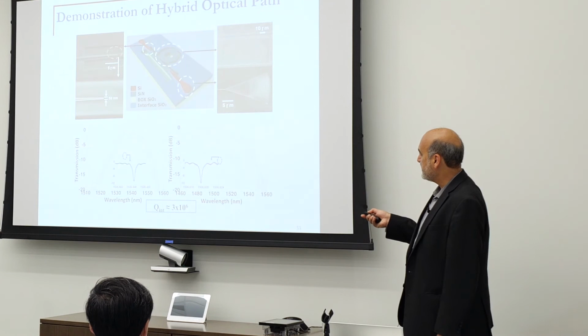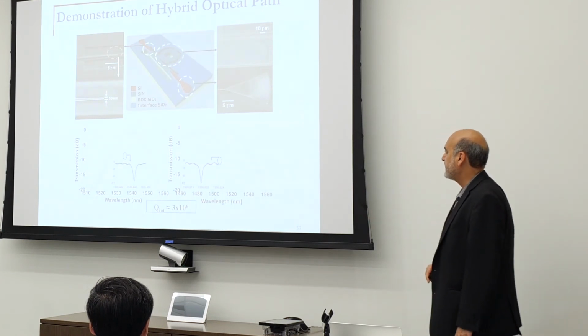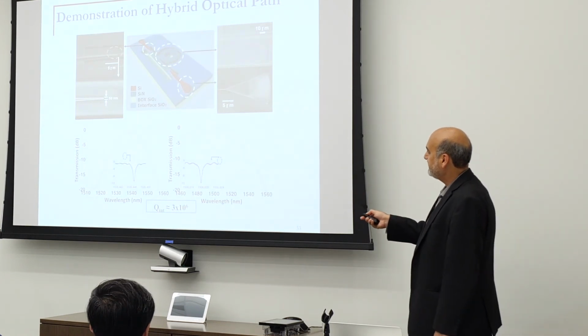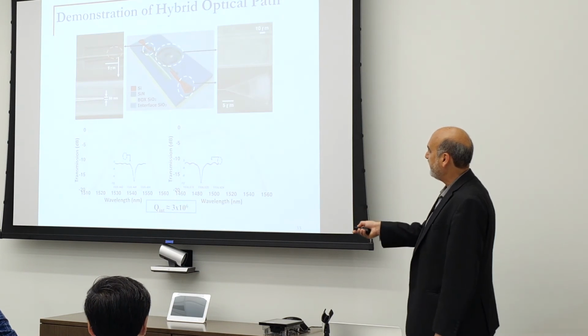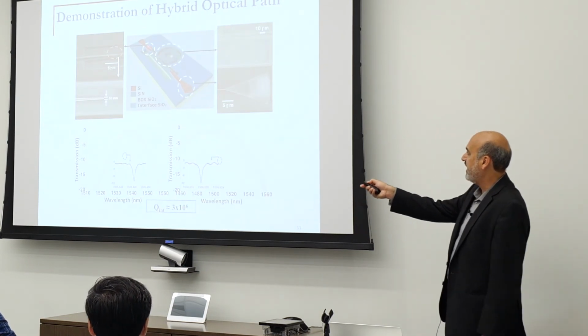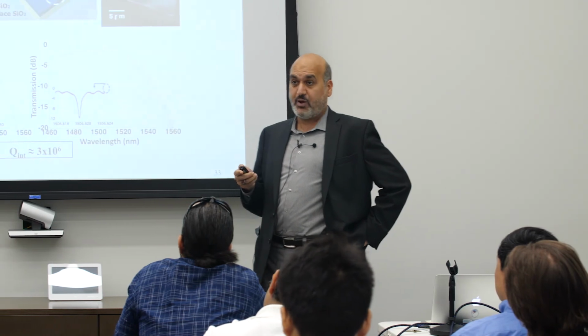This is the transmission spectrum of the device. As you can tell, the loss over a big range is very minimal. That means we have very high efficiency coupling between the two structures, and quality factors of a few million have been demonstrated, showing the good quality of the material. Now, this material platform was developed to address a big challenge in modulation. As I said, pushing toward speed at lower power.